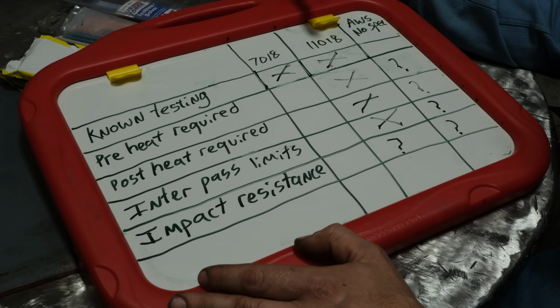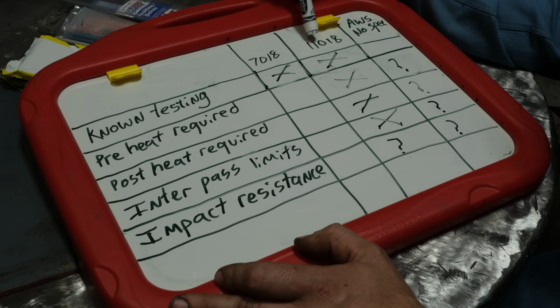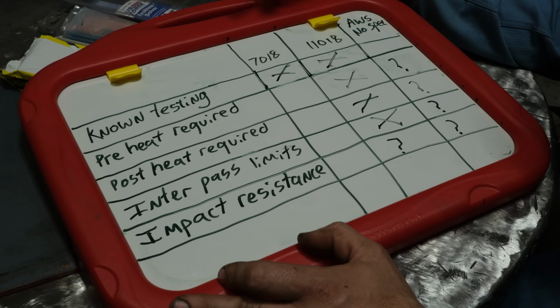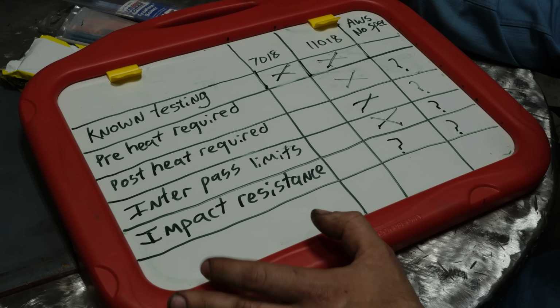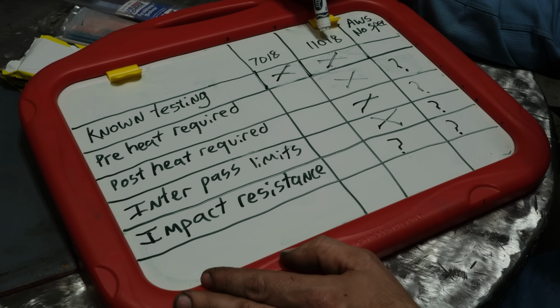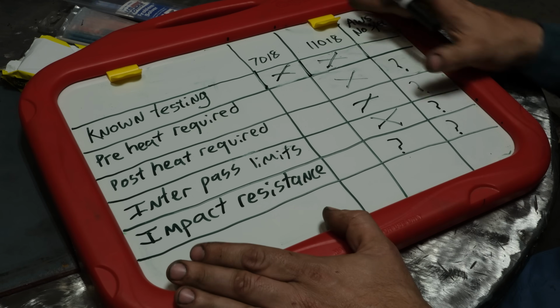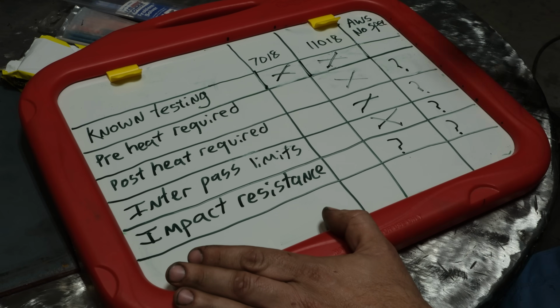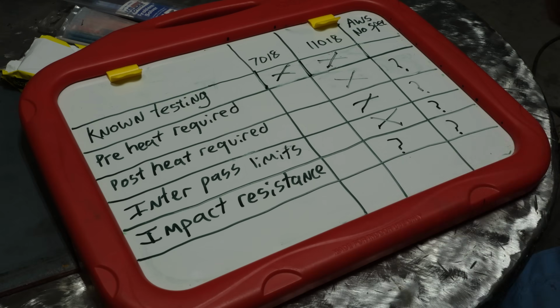Not to mention, hydrogen embrittlement of 11018 welds is a very serious concern. So these rods must be kept in a rod oven, and the material must typically be preheated so that moisture doesn't form on the surface, especially if it's at room temperature, because hydrogen in this alloy and the base material it's designed to weld would be a serious detriment, versus mild steel and 7018, generally not the biggest concern in the world. So I think you have a better idea of this. Let's get into actually doing some welding.